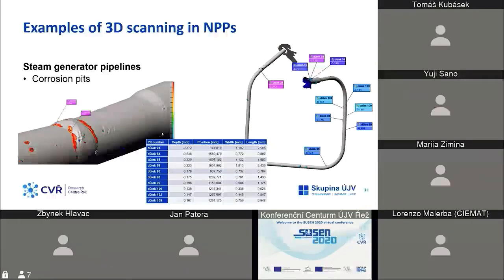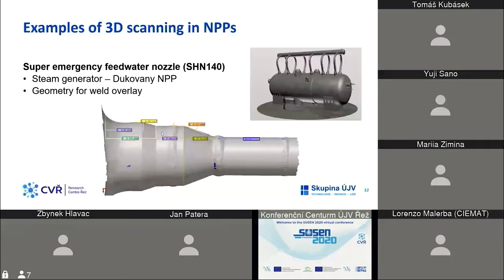Another example of 3D scanning are steam generator pipelines, which are located next to the steam generator. There are many corrosion pits from which a crack may initiate, and this application is also assessed automatically, which means that it automatically looks for the largest corrosion pits and their position. And it also automatically generates some kind of list that you can see here. Another example is the super emergency feedwater nozzle, which is located on the steam generator in Dukovany nuclear power plant. In this case, we had to scan exact geometry for weld overlay qualification.